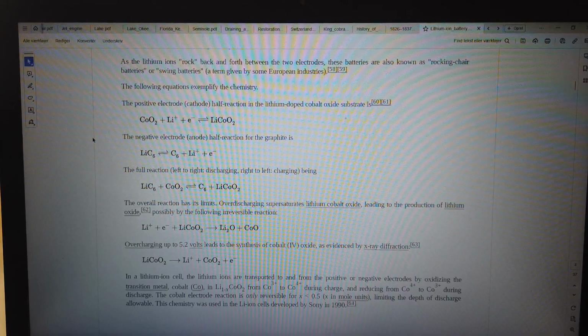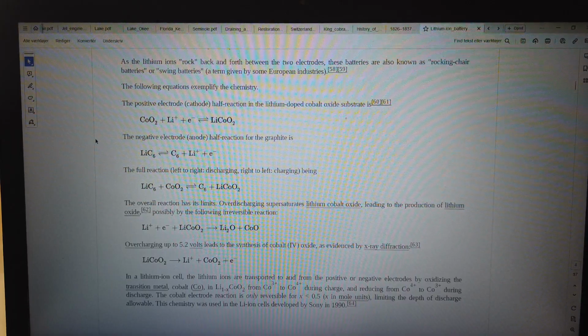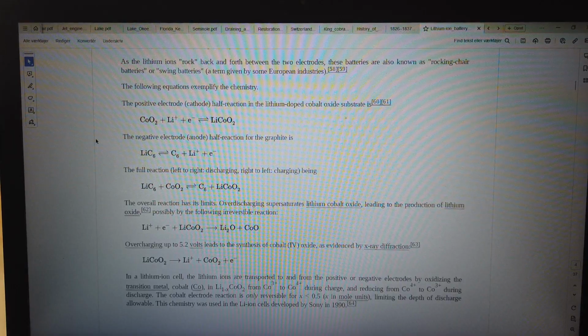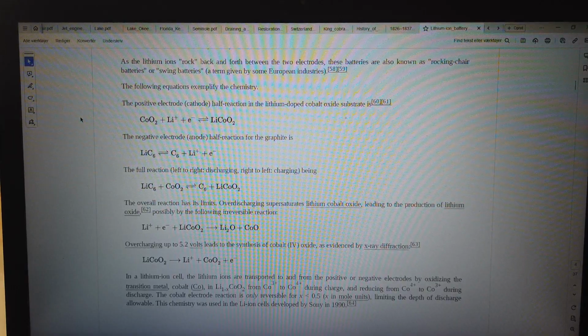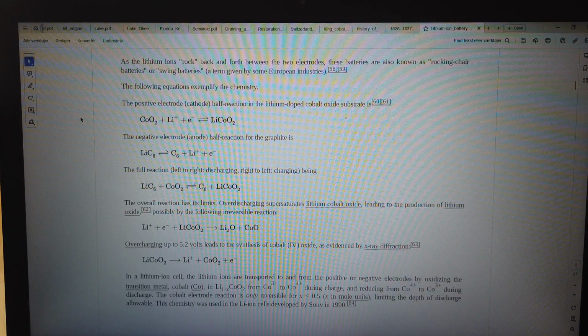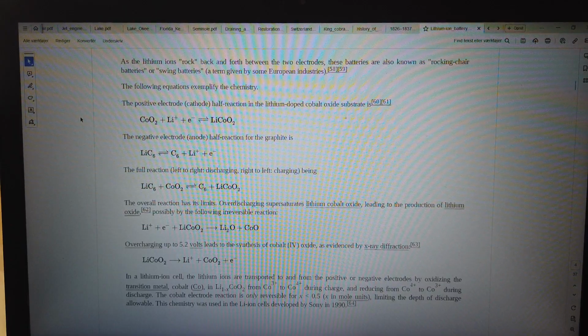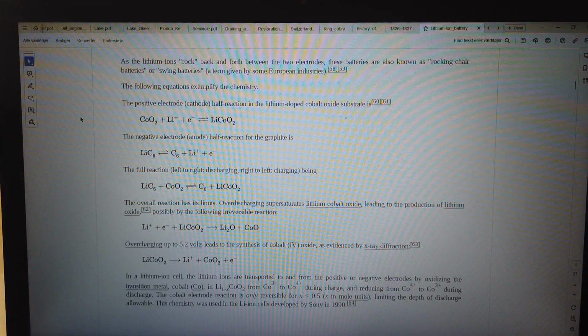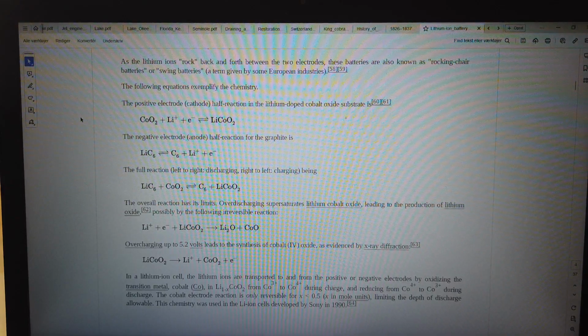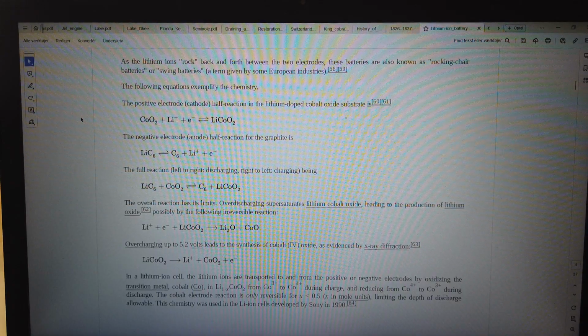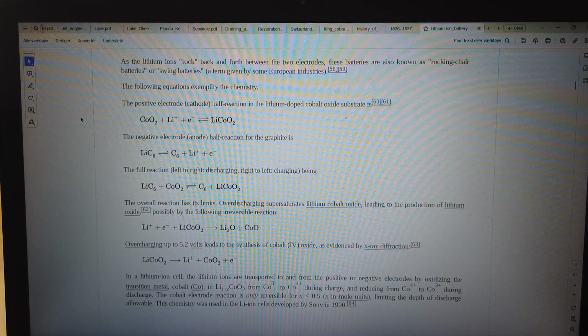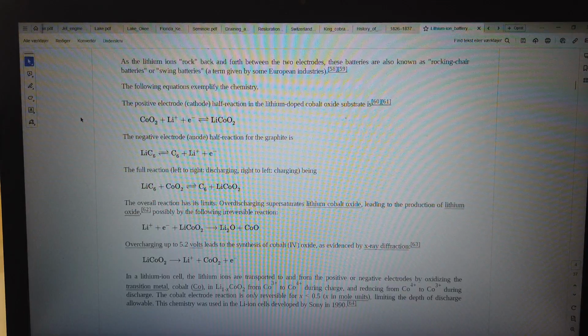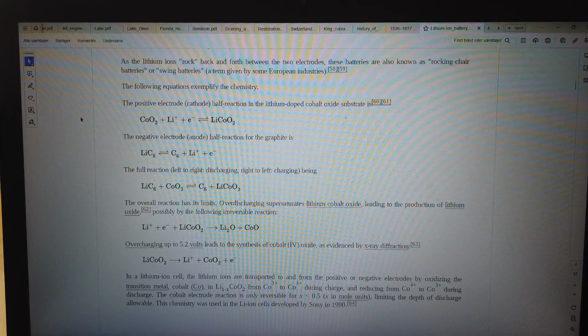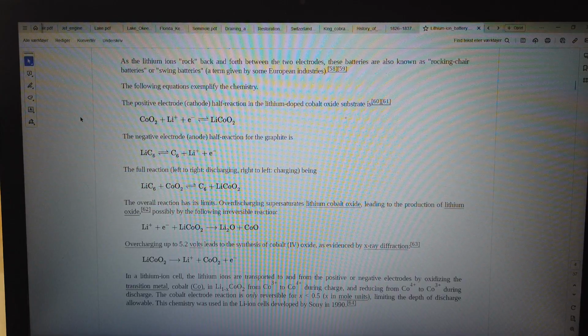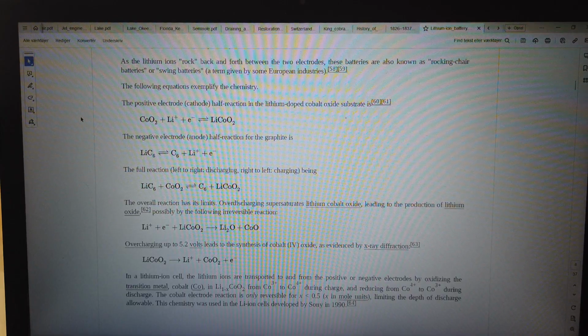The lithium ions are transported to and from the positive or negative electrodes by oxidizing their transition metal, cobalt, in LiCoO2 from Co3+ to Co4+ during charge, and reducing from Co4+ to Co3+ during discharge. The cobalt electrode reaction is only reversible for x less than 0.5 in mole units, limiting the depth of discharge allowable. This chemistry was used in the Li-ion cells developed by Sony in